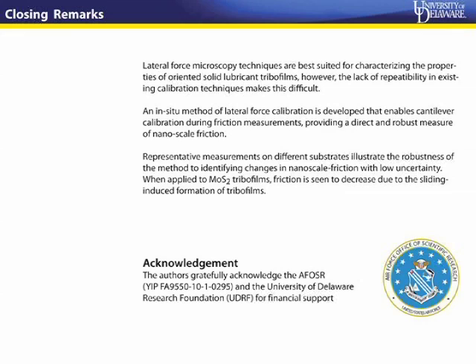So we showed that with an in situ method, there is no need for a separate calibration grating. You can essentially scan on the substrate you're interested in and get both the calibration and the quantitative friction measurements on that very sample. I also illustrated that with the different substrates, we tested this on aluminum, HOPG, carbon, MoS2, and we also saw how friction varies across sputtered MoS2 just as a consequence of sliding.